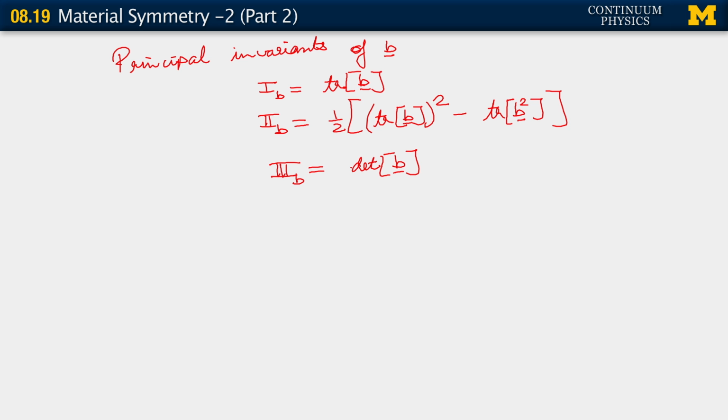So if you have an isotropic material, because it must always be frame invariant and every strain energy function has to be frame invariant, we conclude that for an isotropic material, we must indeed have psi depending upon the principal invariants of B. Okay, so furthermore we could say that you have psi equals psi tilde of B, which could now be a psi.